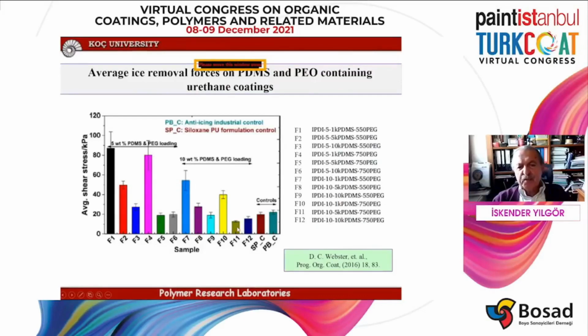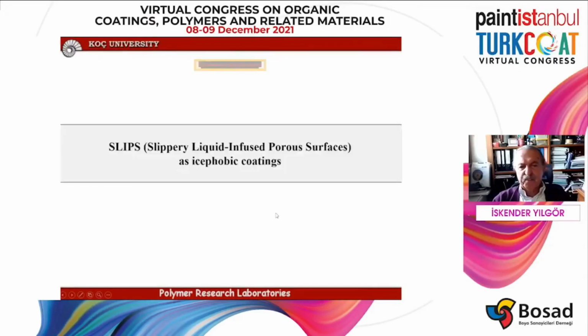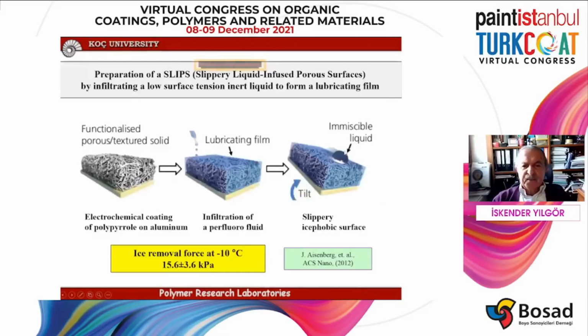So you see they can make better systems, better coatings than the commercial materials available. As you can see, these are around 20 or 25. Now, another one is the SLIPS surfaces, slippery liquid infused porous surfaces. This has been published quite a bit because it comes from Harvard. They even have a company which produces this.